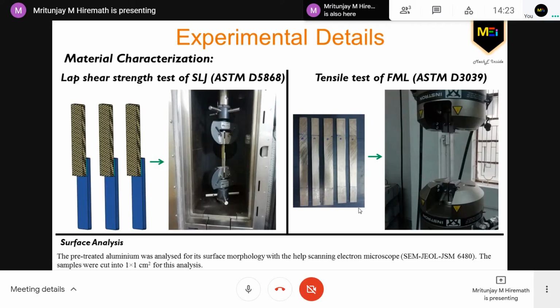The very next test was done for the fiber metal laminate, specifically the tensile test, and it was conducted with respect to ASTM D3039. You can see again, this is a 100 kilonewton UTM machine. Then the fractured surface was analyzed for the surface analysis. Specifically, the aluminium surface was viewed in the scanning electron microscope, and the sample size was about 1 by 1 centimeter square.